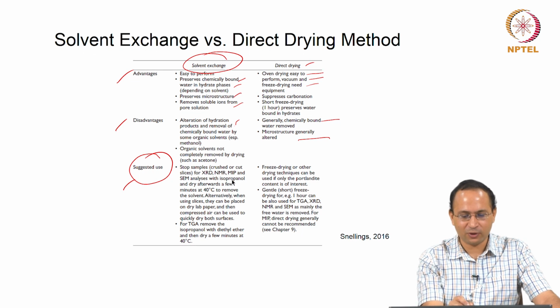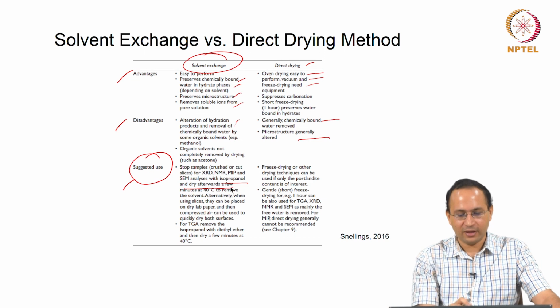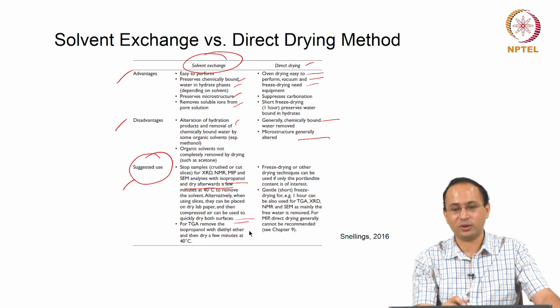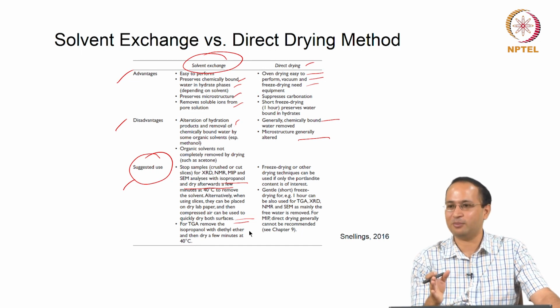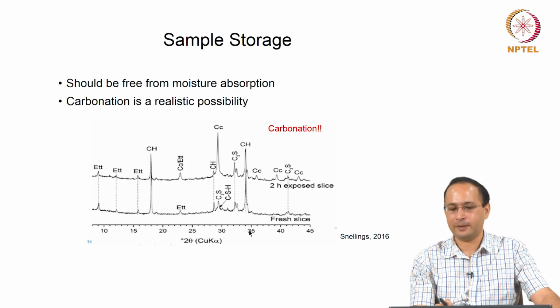Stop samples for XRD, NMR, MIP, SEM analysis. These are the techniques, with isopropanol, and dry afterwards for a few minutes at 40 degrees C to remove the solvent. Alternatively, when using slices, they can be placed on dry lab paper and then compressed air can be used to quickly dry both surfaces. These are some of the processes you can adopt when you are characterizing your samples, right. But you have to make sure that you are following the same process, because a slight difference will also cause a difference in your properties, very important.